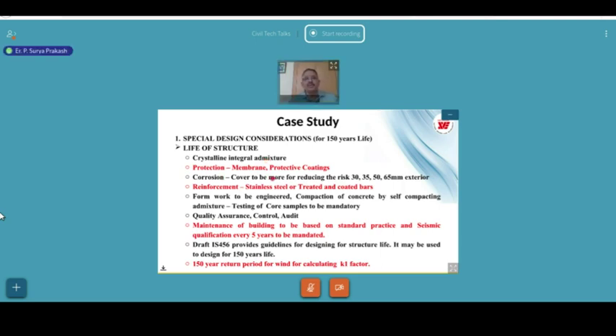Corrosion cover to be more for reducing the risk. So we have specified minimum cover 30, 35, 50 and 65 mm exterior covers. And reinforcement, either use stainless steel or treated or coated bars. Treated and coated bars, that means you can protect the reinforcement by doing the perfect, but not at the site. I have seen anti-corrosive coatings on the site, which is only an eye wash. It has to be a factory coated treatment.